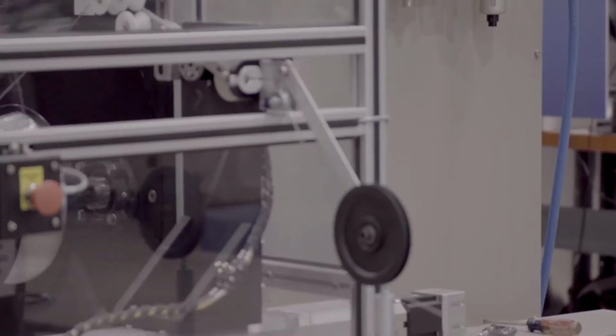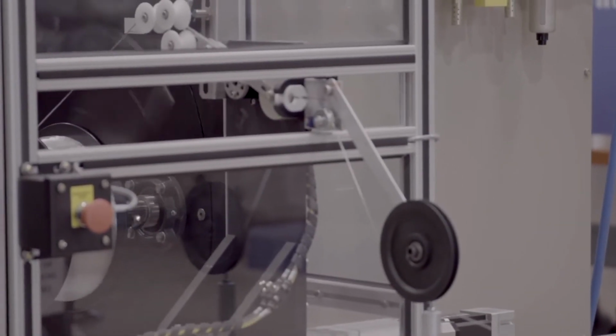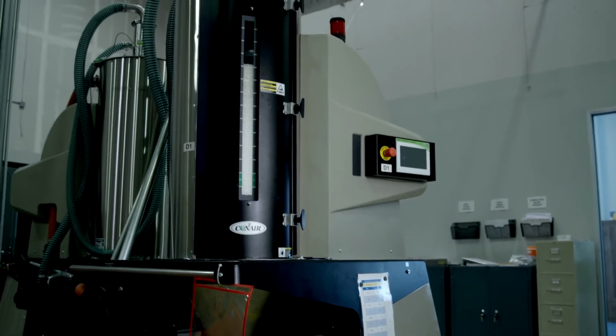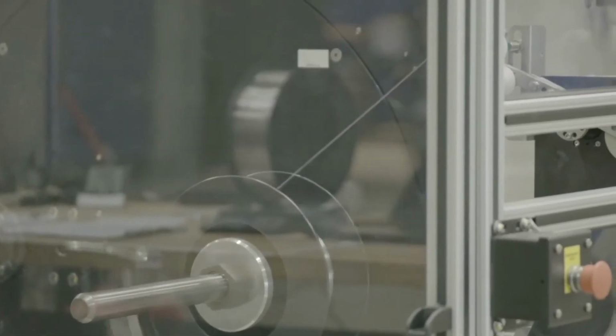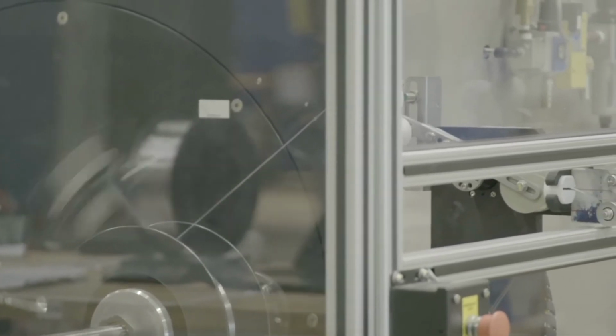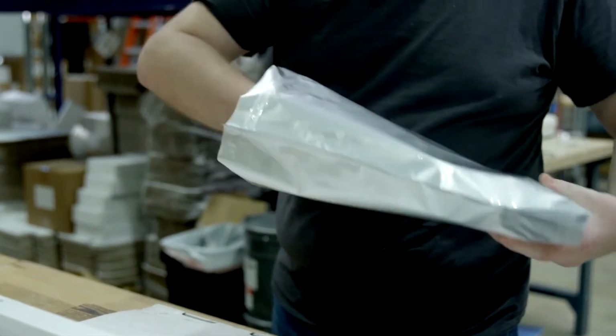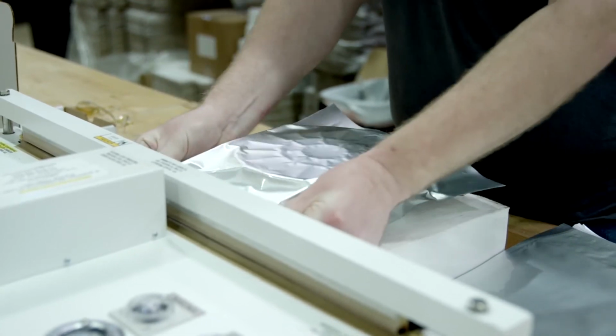In fact, the first step to extruding 3D printing filament from pellets is drying the material according to the resin manufacturer's recommended drying procedures. We use industrial hot air desiccant dryers that circulate hot and dry air with a dew point below minus 40 Celsius through the resin hopper. After the filament is extruded and wound onto spools, it's dried again before packaging to make sure it's completely dry. Then it's vacuum sealed with a desiccant pouch.